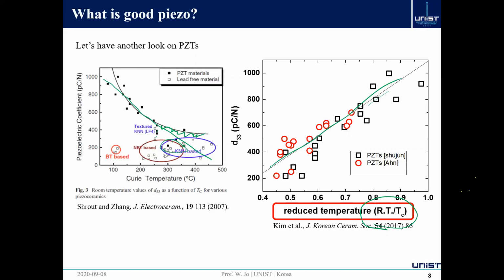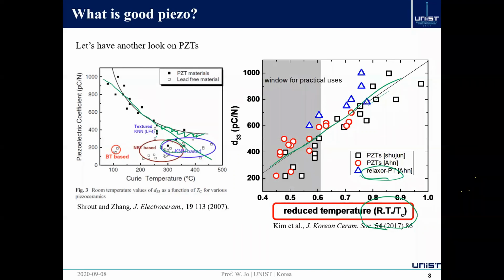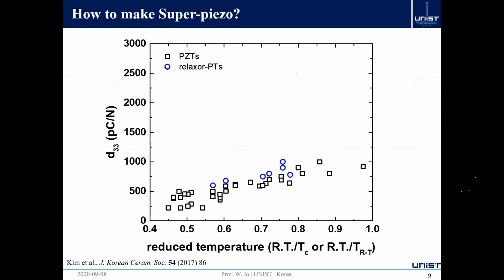Then why did I do this? Because this gives us a really good insight into how to enhance the piezoelectric properties of new compositions. I also put the relaxor PT-based materials too. They also fit very nicely into this line. So you don't really have to think about a practical window here. This is exactly the data I showed you in the previous slide for the PZT together with the relaxor PT type of ceramics, the D33 as a function of this reduced temperature. And this line really goes linearly.